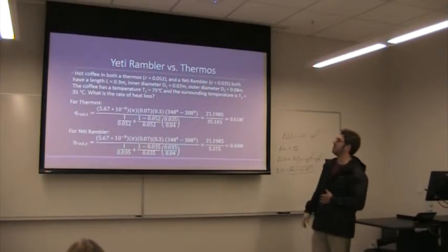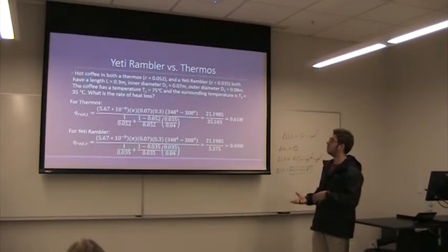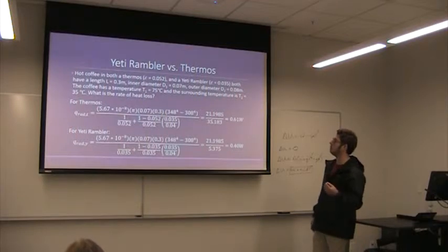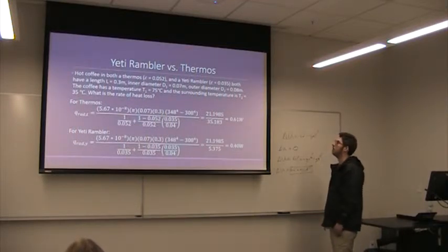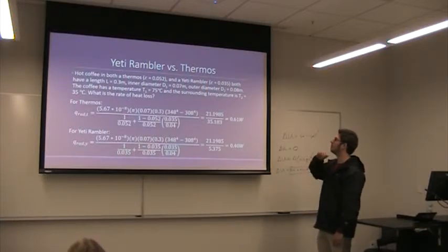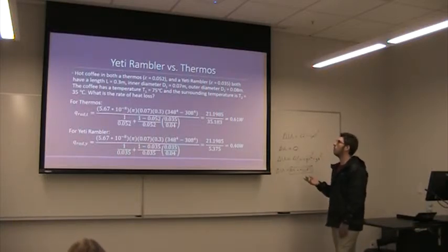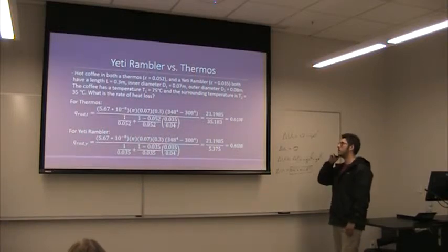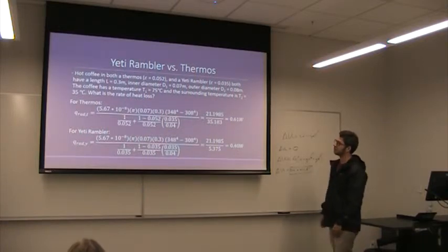They are both filled with coffee, where the coffee is at the same temperature and the surroundings are at the same temperature. For the thermos, the silver coating, I use an emissivity of 0.052, and for the Rambler, it has a copper coating, or polished copper, which has a value of 0.035.